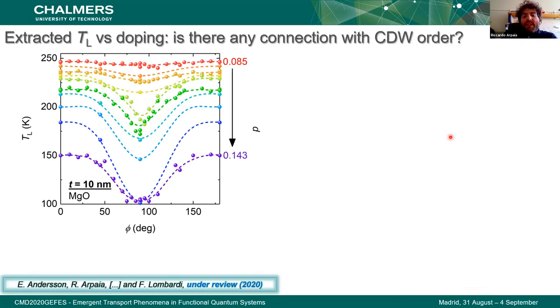We have done this investigation as a function of the doping, and we've seen basically that this effect of anisotropy of this T_L, the linearity temperature, where the linearity of the R versus T finishes, is present in the same range in which charge density wave is present. So we just asked ourselves, can this be connected with charge density wave? And this is indeed what we have seen.